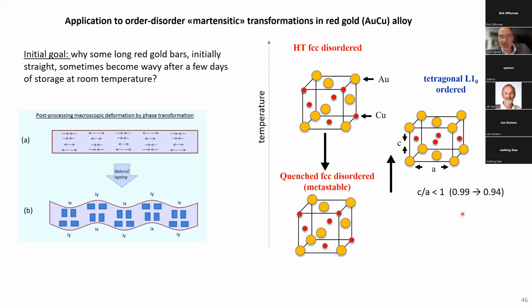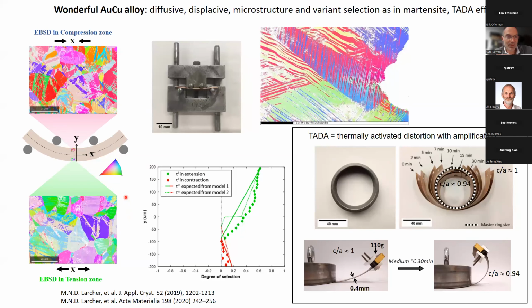To check the hypothesis that it could be oriented variant selection, exactly as in martensitic transformation or in shape memory alloys, we maintain in bending condition a red gold bar that was initially quenched, fully disordered, and we put this device in a furnace to activate the diffusion and, it is strange, but to activate the martensitic transformation, I call it like that. And we form these variants, these laths. You can see the difference of colors, and it is due to variant selection.